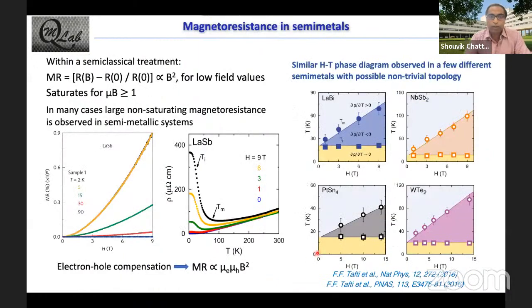Okay, so just to give a brief background, as you all probably know, if we talk about a semi-classical treatment, what you generally expect is that your magnetoresistance follows B squared behavior at low fields, and then it saturates. If you look at typical metallic systems, these are of the order of 2 to 3%. But recently what was realized is that there is a class of intermetallic systems where this magnetoresistance can be very high, of the order of 10 to the power 6.